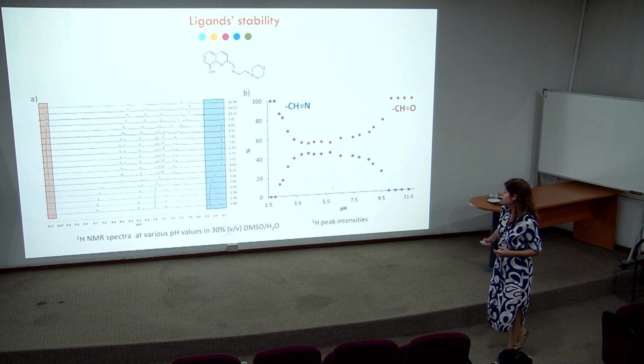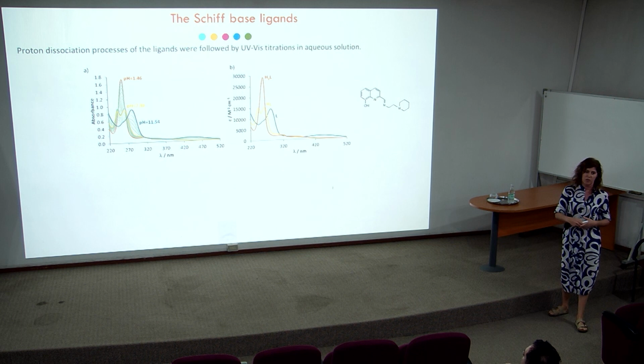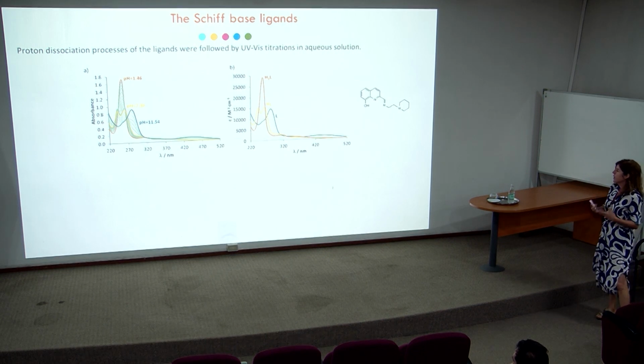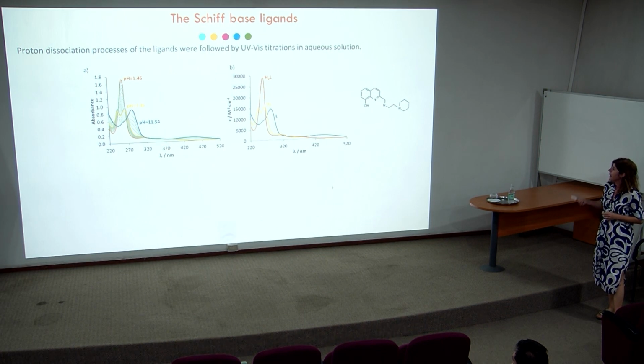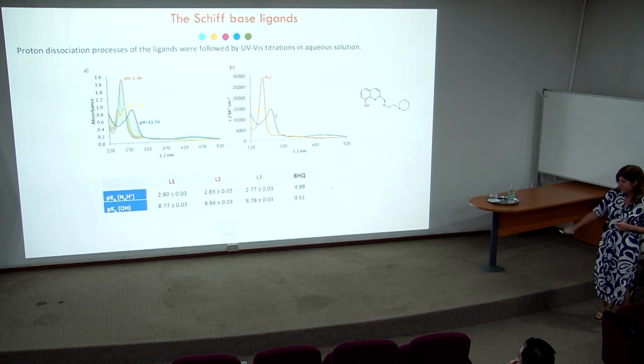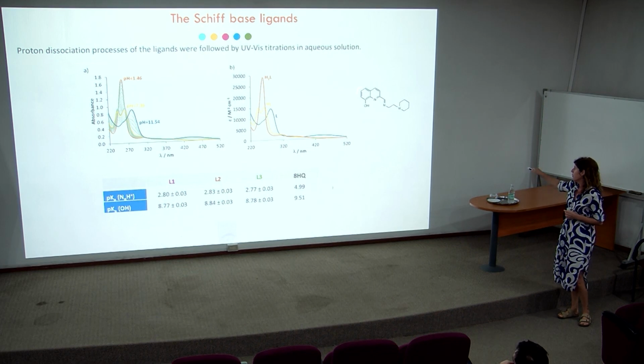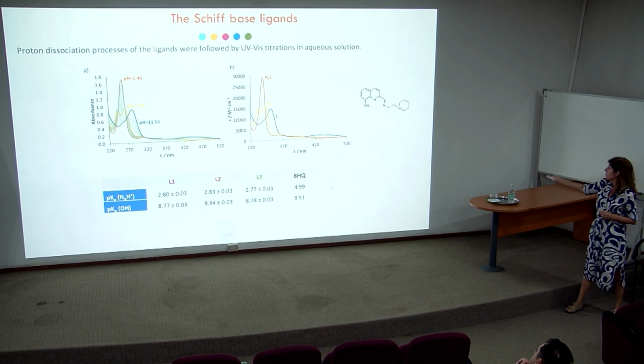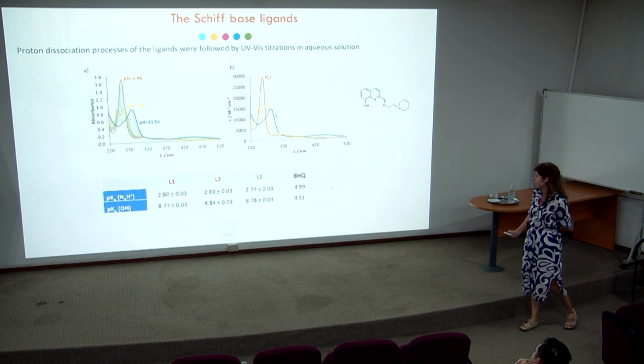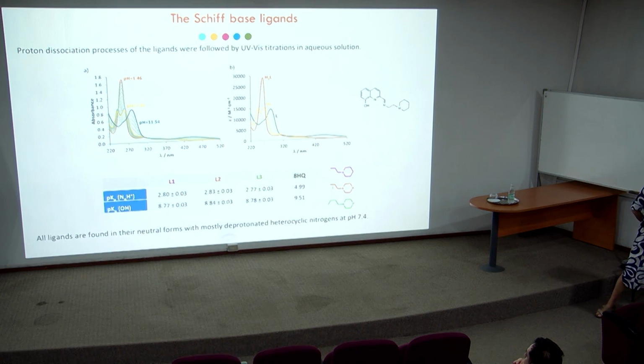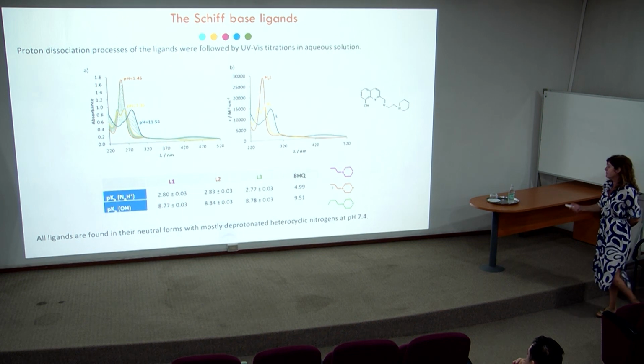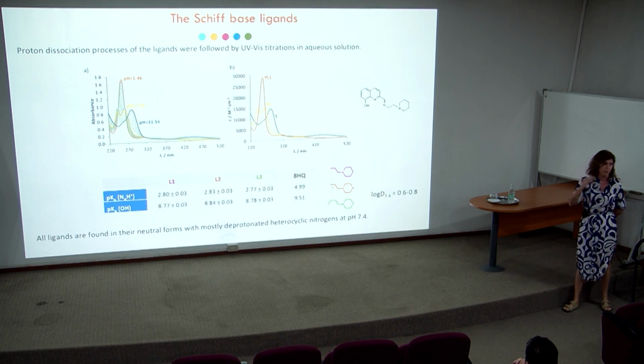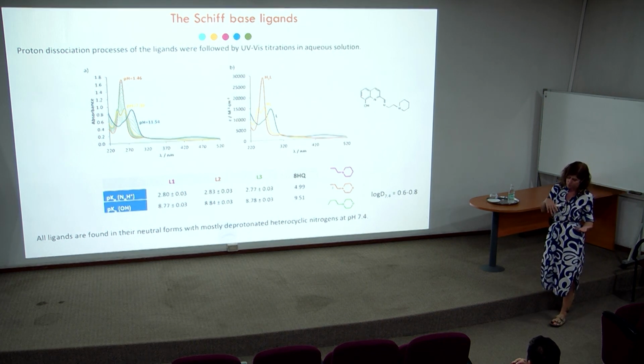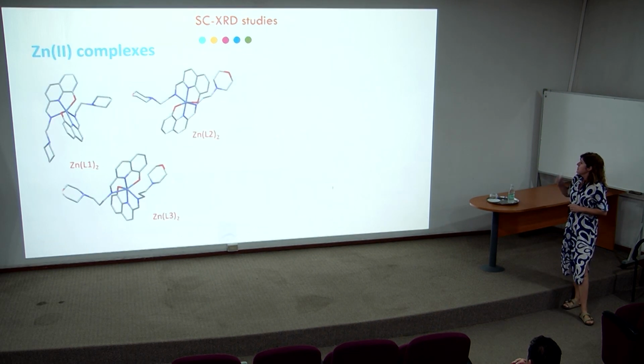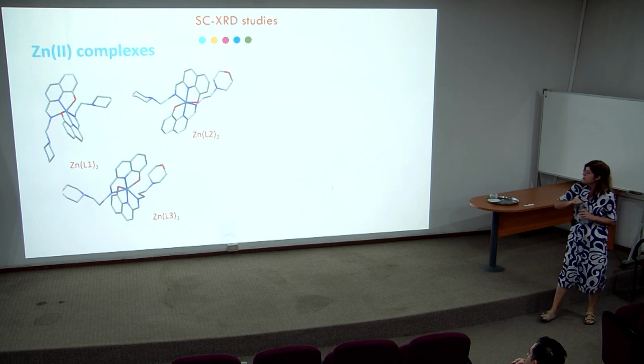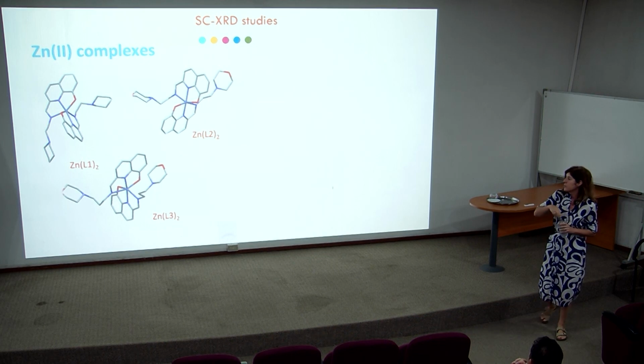So these ligands are not so stable, but still we could determine their proton dissociation constants using spectrophotometry, because quite low concentrations are used, and these are fast measurements. And we could obtain the pKa values for the pyridinic nitrogen and for the phenolate. Okay? We could not detect this process because this is not a chromophore, although it can be protonated also. So again, the ligands are neutral at physiological pH. And their lipophilicity is now a bit lower. So these compounds are more water soluble, although not that stable. So next, what we did was to prepare the metal complexes. These systems crystallized quite easily, and we obtained crystal structures for all the complexes.